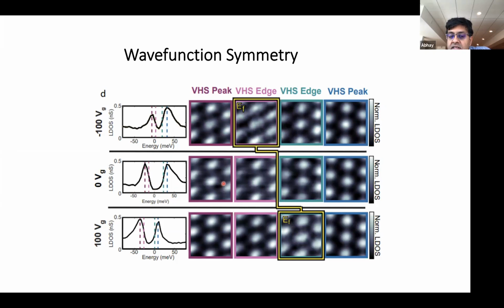The local density of states looks approximately threefold symmetric, and it's pretty much the same for all energies at low energy. I say approximately because in these samples at the time, two years ago, there was always a small amount of strain present, and this strain always breaks the threefold rotational symmetry. But perhaps you'll still agree that, for example, here it looks pretty much threefold rotationally symmetric.